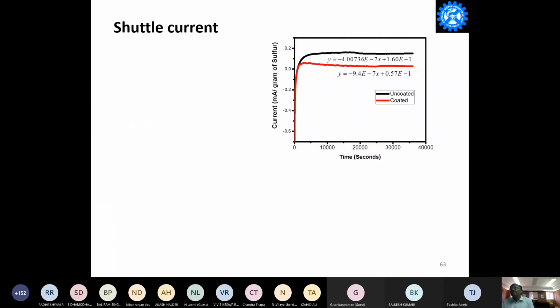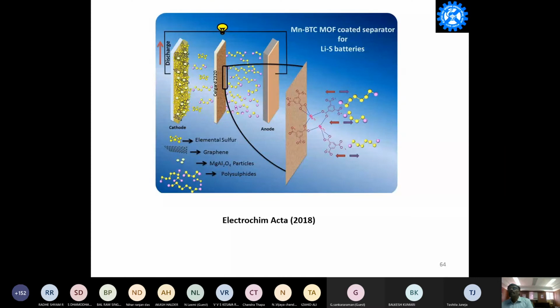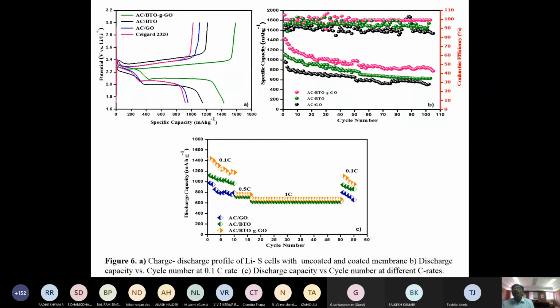And we have measured the shuttle current. We found very low shuttle current for the coated membrane, the red one, and for the uncoated membrane, the shuttling was more. So we got a lot of self-discharge. This is the schematic diagram of the MOF coated membrane. So when we use the MOF coated membrane between the two electrodes, because of the electrostatic interaction, all these lithium polysulfides are attracted by the MOF surface, and the cycling efficiency was improved. And similarly, we have synthesized barium titanate, and we have grafted the barium titanate.